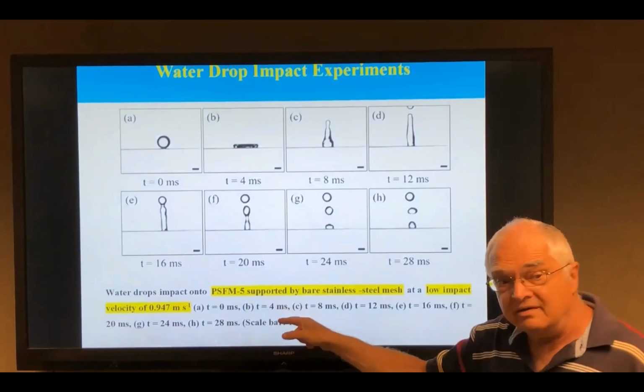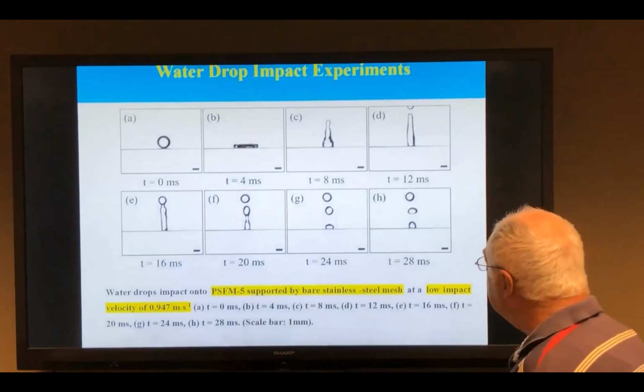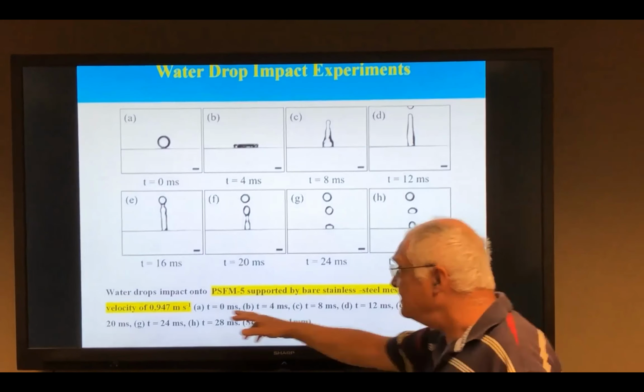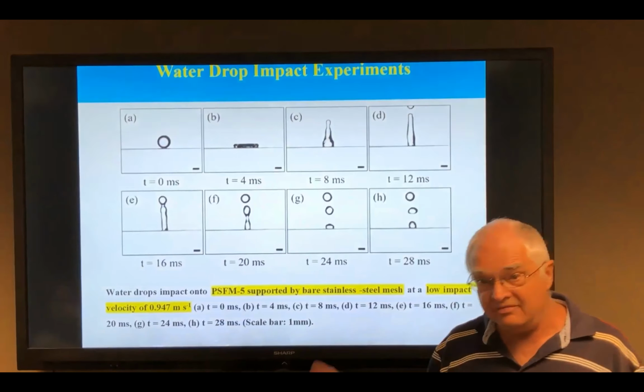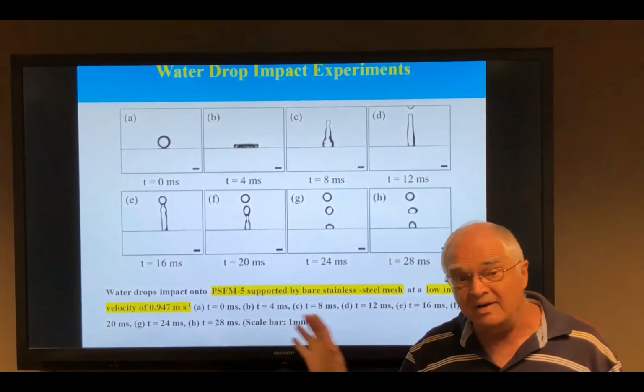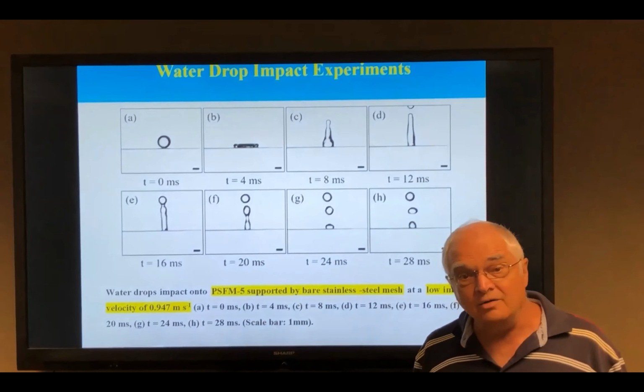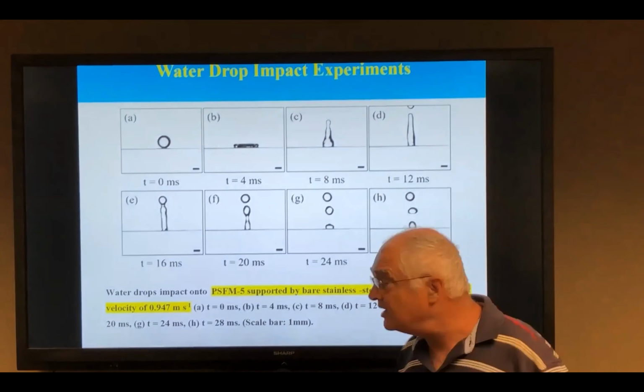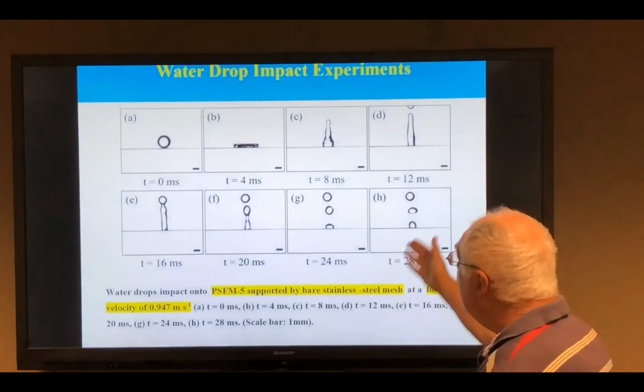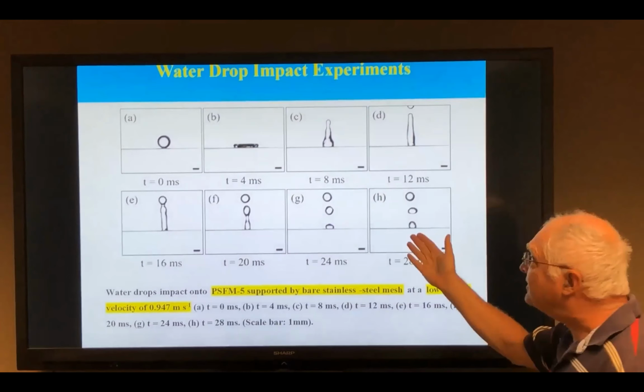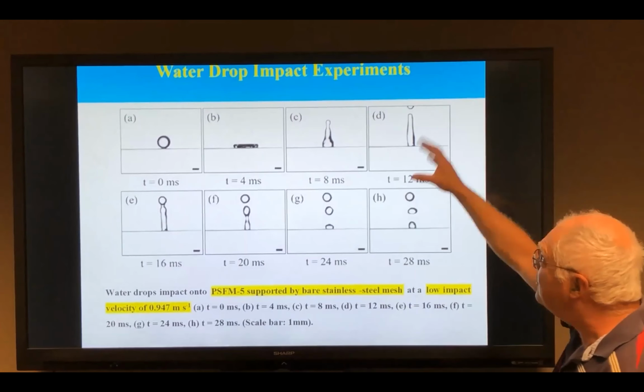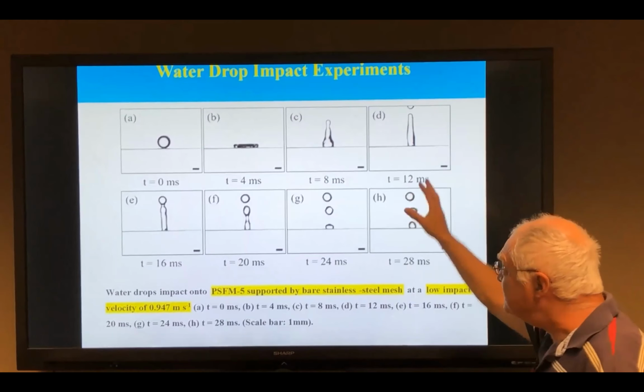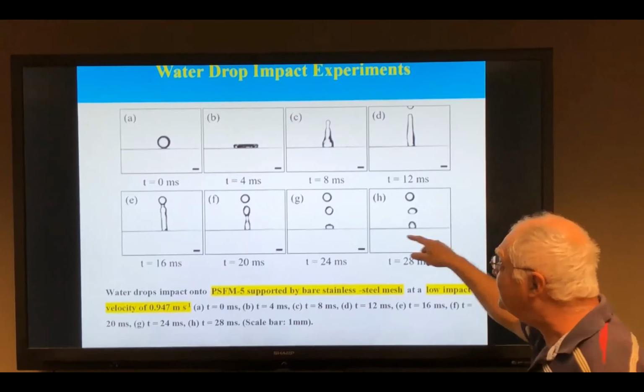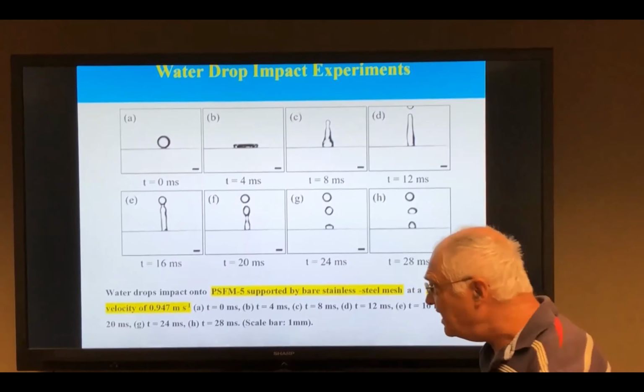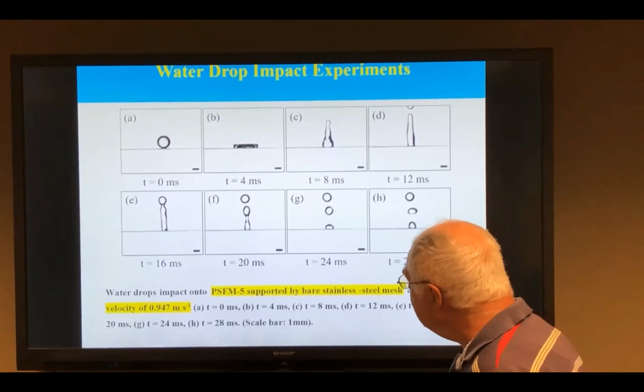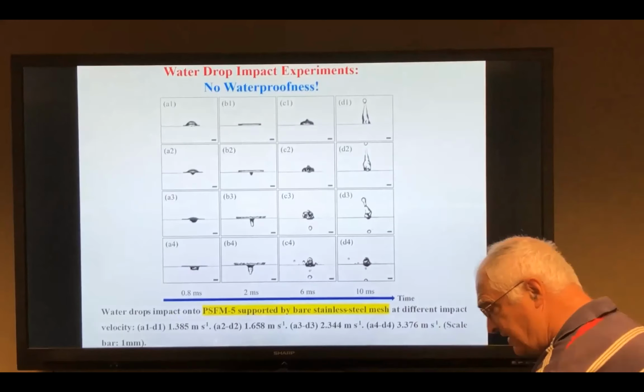Now we are going with our membrane. This is not a grid, this is our membrane. We drip a droplet at a relatively low velocity, and this is low even in terms of raindrops. I'll mention the raindrops later on, but they go up to 5 meters per second. So this is 1 meter per second, and our membrane behaves perfectly. The droplet hits the membrane, bounces off, and you see many interesting phenomena, but nothing goes through the membrane. Now let's take a look at what happens at a higher speed. Please go ahead.